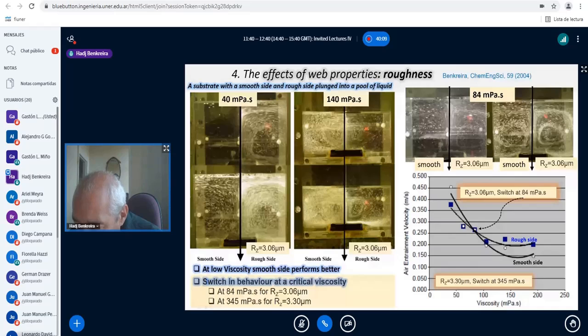So effectively, here is the result of the data. This is the air entrainment for the smooth side, and this is the air entrainment for the rough side. Above 84 millipascal, the rough side is performing better, and below 84 millipascal, the smooth side is performing better. So as you see, the roughness has a very complicated and non-linear type of effect. Before we did this experiment, the idea was if you use a rough substrate, you will always coat faster, which is not true. You will only coat faster with a rough substrate above a certain viscosity.